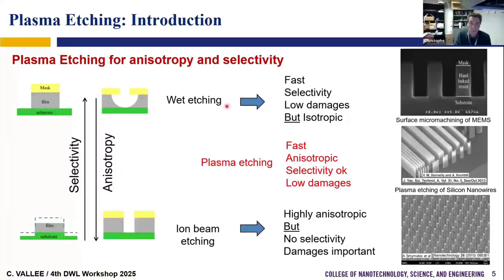We can use different etching methods. You can have a pure chemical etching, like wet etching. A pure chemical etching can be very fast and very selective due to the chemistry, but usually it's isotropic, so you are etching in all directions. You can use ion beam etching, where you only sputter with ions, so it can be highly anisotropic because ions come perpendicular. But usually you don't have chemistry, so you don't have selectivity, and you may have a lot of damage.